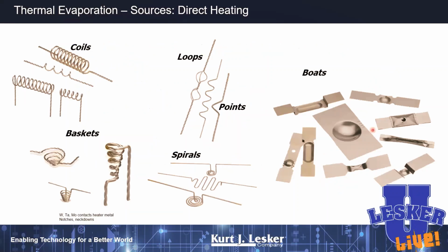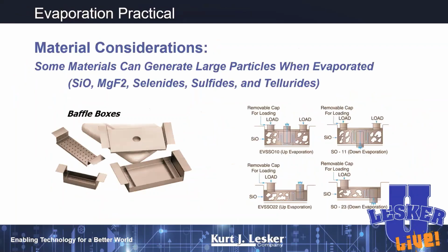Again, I showed you these boats. Again, these are great for making relatively thin films, because you can't put much material in them. You can evaporate from rods by putting coils in there in our systems. If you do want to evaporate down, for example, if you've got a substrate that needs to be coated below your source material, there's some fairly sophisticated boats out there that'll evaporate down. If you've got a material that spits a lot, you can put it in what's called a baffle box, where we put the material in the box and then cover it up with a sort of a shield to try to mitigate big clumps of material spitting out at your substrates.